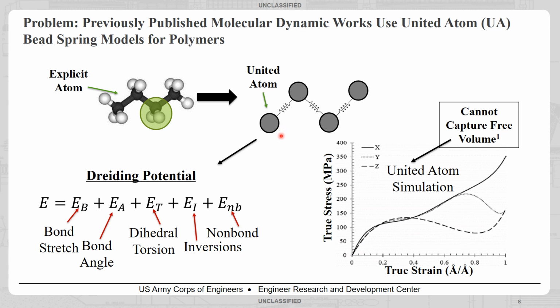It does have some good applications. It reduces the number of atoms in your system, it removes hydrogen atoms so you can take larger time steps, and it has been shown to capture stress strain behavior, or especially yielding, quite well in polymers. The problem is that post the yield point, a lot of uncertainty exists because it doesn't do a good job at capturing free surface formation, and it underestimates the friction to friction contact that you would have if these hydrogen atoms were present.